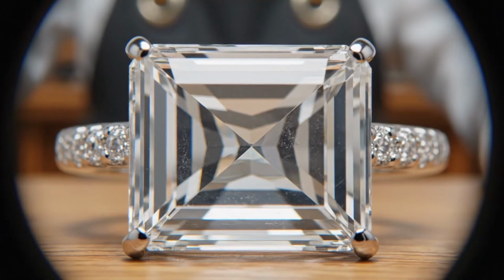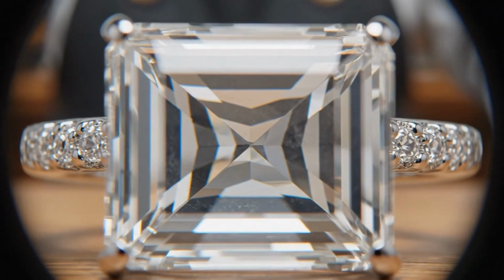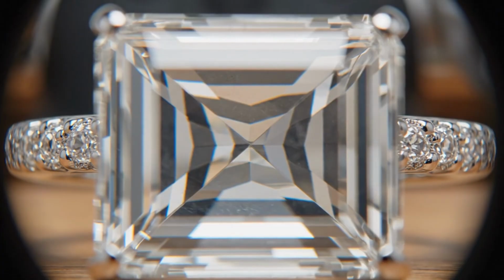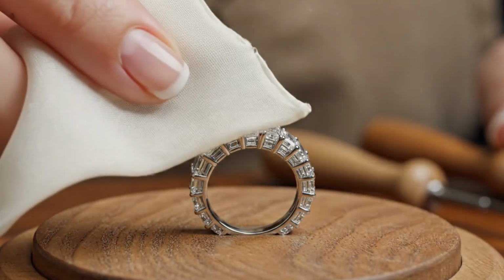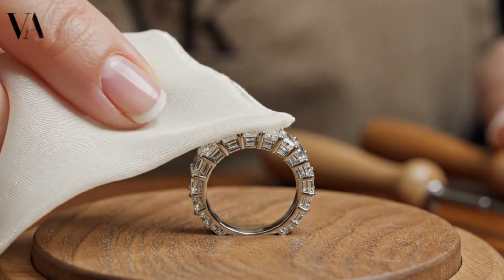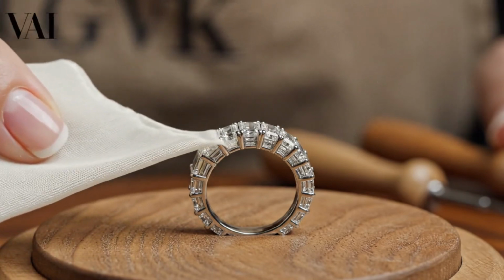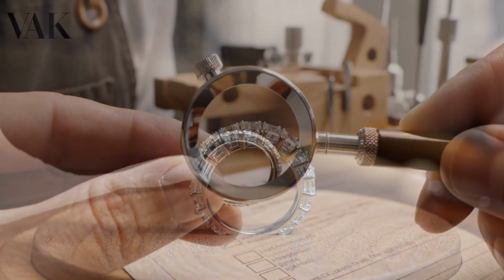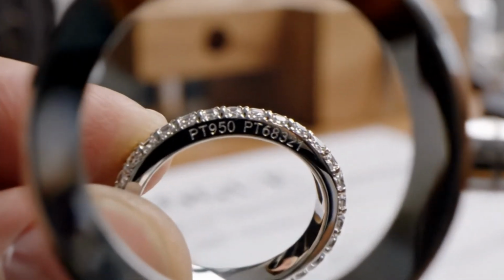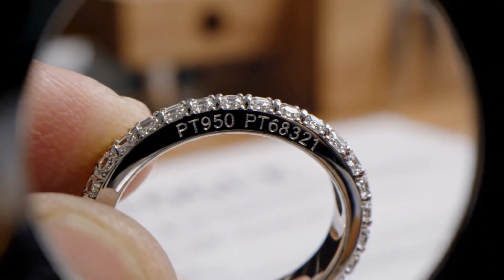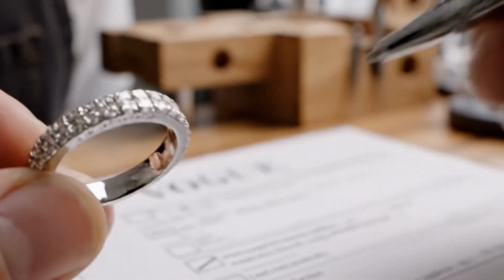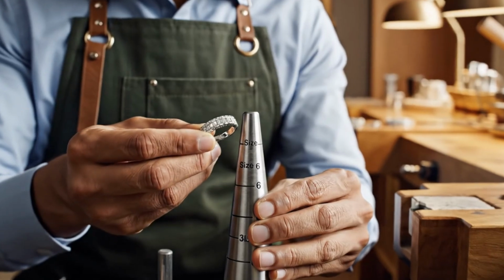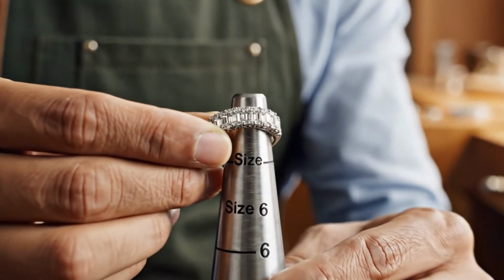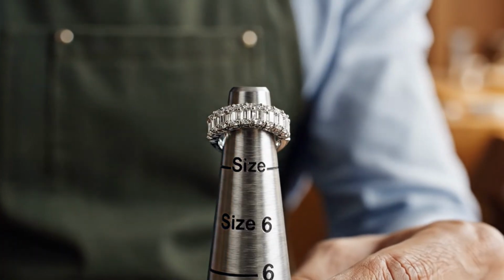Under the microscope, we verify the culettes are open and clear, allowing light to pass through the stone without any obstruction or interference. We run a silk cloth over the prongs in every direction, feeling for the slightest snag that would indicate a rough metal burr. The laser inscription is verified against the work order, ensuring the purity stamp and serial number are crisp, deep, and perfectly legible now. We measure the final ring size on a calibrated steel mandrel, ensuring it hits the center of the line for the specific client.